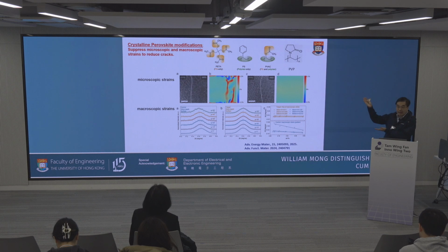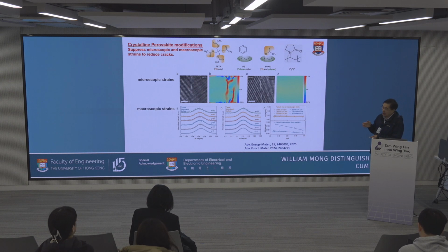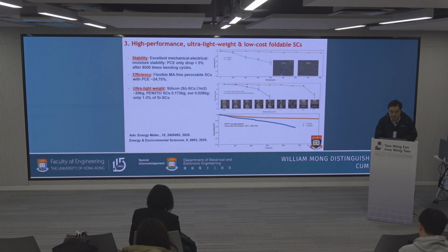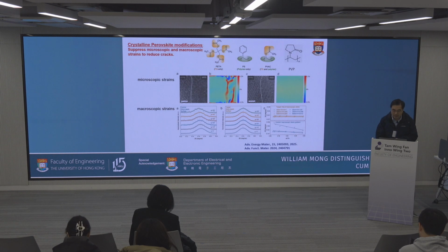We can make OPV as we showed you in the last slide. How about perovskite? Perovskite is not just a matter of a flexible or foldable substrate making it foldable. The perovskite itself is a polycrystalline material, so it will crack when you bend it hard. So we try to address the issue, and we first study, let me see if I get you the old version. Indeed, this is the old version. Oh, apologize. Indeed, we address the stress in two ways.